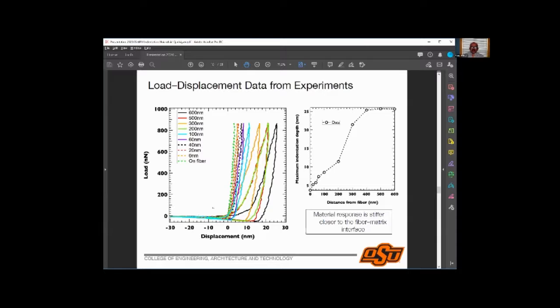And the answer is yes, because for example, if you look at this loading and unloading curve, they are not both ending up at the same point. If you were loading and unloading in pure silica, even with an AFM tip, then these two curves would completely overlap. If these two curves completely overlap, that tells us that the deformation is primarily elastic. Here, what we know is that it is not primarily elastic. There is something other than elasticity, whether it is large-scale plasticity, or other time-dependent behavior, or rheological behavior, or viscous behavior, we don't know. And honestly speaking, for our purposes, it doesn't matter because we are not looking at the loading curve.